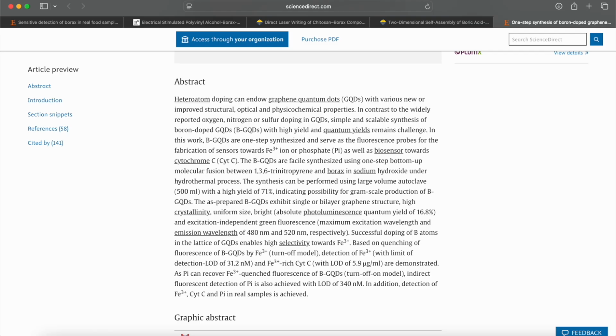As phosphate can recover the iron 3 quenched fluorescence of boron graphene quantum dots, indirect fluorescent detection of phosphate is also achieved with an LOD of 340 nanomolar. In addition, detection of iron 3, cytochrome C, and phosphate in real samples is achieved.